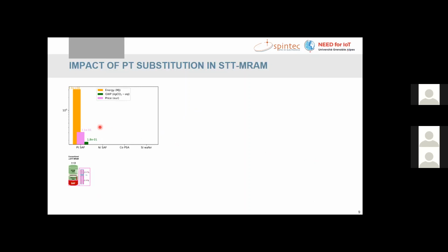So here I just show you some numbers of the energy, the global warming potential, and the price that is required for obtaining the platinum that is contained in the SAF structure. So this is for thin film level, and then for a 300 millimeter wafer. Then I did the same for the nickel alternative. And as you can see, there are strong reductions in all terms: energy, global warming potential, and price. You can see this on a logarithmic scale.